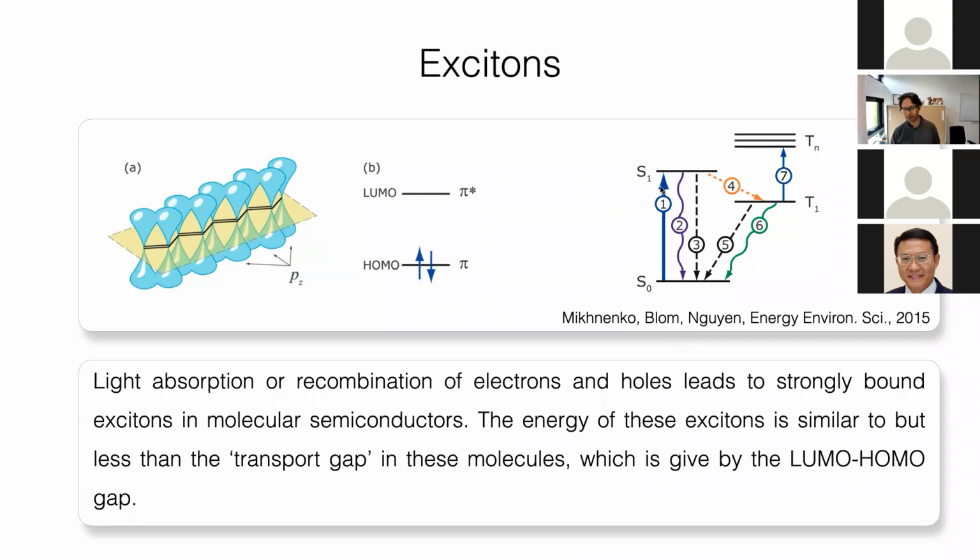once you get the formation of excitons, which are normally denoted with this S1, S2 terminology for singlet excitons, there are a number of processes that can happen. You can have radiative recombination, as illustrated by this process 2, which gives you light back out. And of course, this is of interest to us in LED or lighting applications. You can get non-radiative recombination, as illustrated by process 3, or you can get intersystem crossing to spin 1 triplet exciton states. And so what we are really interested in for the purpose of this talk is exciton transport, so how we move excitons from one site to another. And what I'd like you to keep in mind from this diagram is that excitons have a finite lifetime.